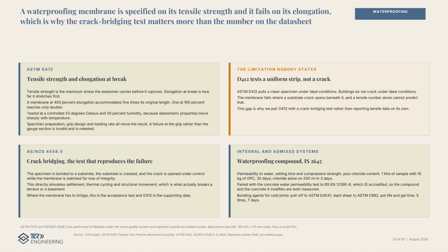A waterproofing membrane is specified on its tensile strength and it fails on its elongation. ASTM D412 measures both maximum stress before rupture and how far the elastomer stretches first. A membrane at 400% elongation accommodates 5 times its original length. One at 100% reaches only double.